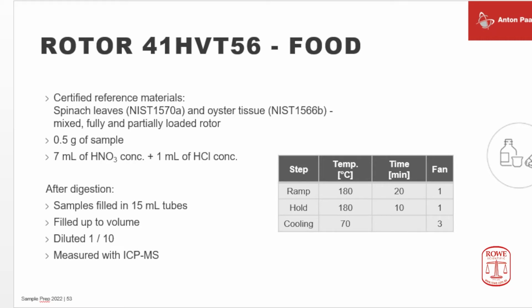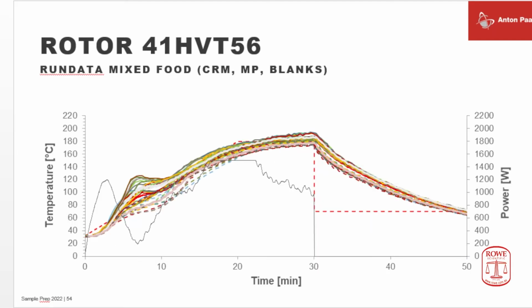This is a printout that you would get at the end of such a reaction, and what you see is, as we have used a mixed set of food samples, very sluggish in reaction to very quick in reaction, you see that the temperatures developed in here were quite different depending on the reaction nature of the sample. There were some exothermically reacting samples that are showing temperature peaks right here, and there were blank samples that followed exactly the pre-programmed temperature. From this picture you can see you had a set of samples that reacted quite differently. That's okay, the instrument is made for that.